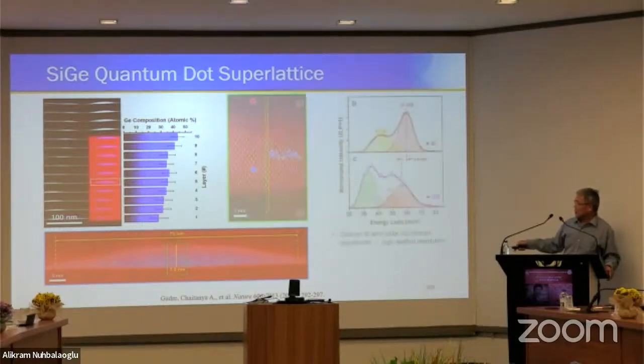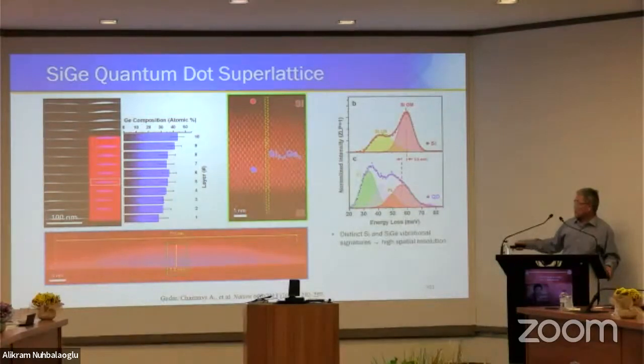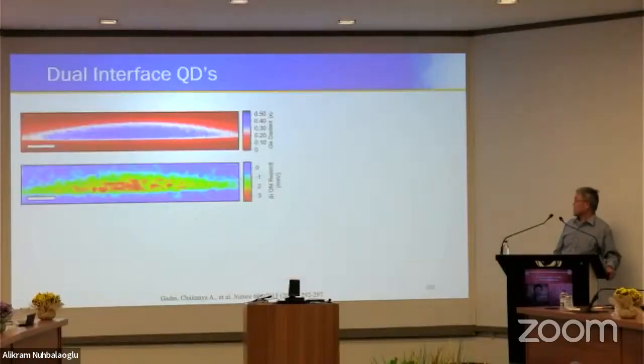The bottom interface is very sharp. It is constructed very sharp. The top interface is a gradient, which is diffuse. The composition of the silicon germanium ratio is changing gradually across this interface, but abruptly along that interface. This is demonstrated here. This also shows there's a new phonon mode, and the optical mode of silicon has a shift. And this is similar to the silicon carbide.